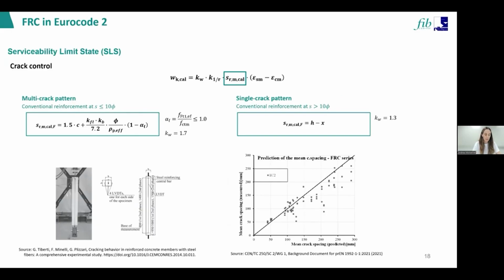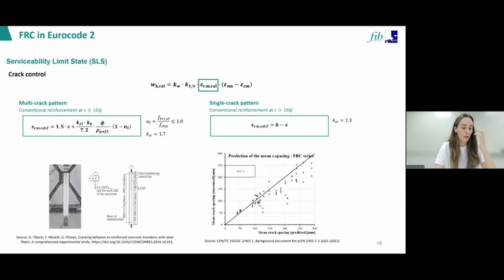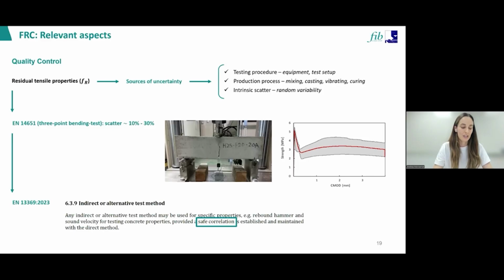effect provided by fibers. So beyond all these code provisions, there are still several practical aspects that remain particularly relevant for the structural application of fiber reinforced concrete. Among them, one of the most important challenges is probably the characterization and quality control of the post-cracking behavior of the material. One of the main challenges associated with fiber reinforced concrete in general is the intrinsic scatter affecting its residual tensile properties. This variability is related to several sources of uncertainty associated with the testing procedure itself, with the production process, and also the intrinsic variability of the material.